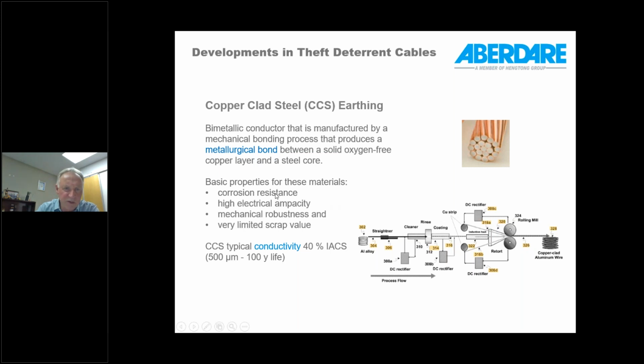So the basic properties of these materials are high corrosion resistance, reasonably high electrical ampacity, mechanical robustness, and very limited scrap value. So if scrap of copper-clad steel or copper-clad aluminium is melted together with copper scrap, it can really cause havoc with the scrap dealer or recycler, through the contamination that this would create.